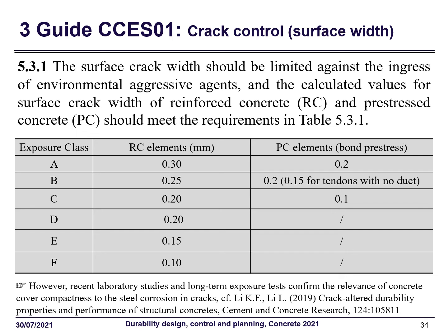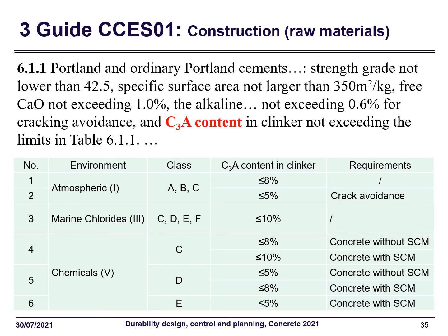And another control is the crack control with respect to durability. Here on the table, we limit the surface crack opening width with respect to exposure classes. It's also very similar to the requirements of Eurocode, but here, I would like to say that from recent laboratory study and long-term exposure tests, they confirm that the crack surface opening width is not very relevant to the corrosion in the crack. They confirm also the relevance of concrete cover compactness. So we think that with further study, perhaps this requirement on the surface opening width will not be so important. And then we'll continue on the requirement of construction.